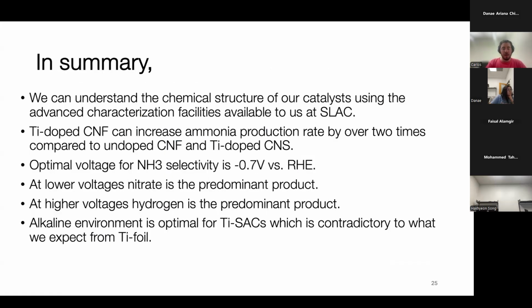And yeah, in summary, we can understand the chemical structure of our catalyst using the advanced characterization facilities that we have here at Stanford. We partner with SLAC, which is our closest lab that we can go to do all these XAS and XPS and XRD experiments. We have shown that the titanium doping in the carbon nanoflowers can improve the ammonia production rate by over two times compared to the doped carbon spheres and the undoped carbon nanoflowers.